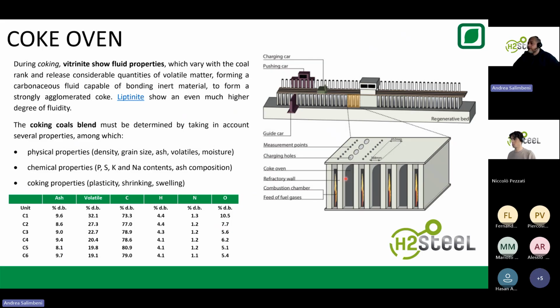These are the chambers where the coal is charged, and these are the chambers where heat is produced by burning the gas. In this case, at these conditions, the specific coking coal like vitrinite and liptinite becomes fluid and degrades, producing a highly porous, really strong carbon-rich material, which is named coke, which presents much more structural properties, compression strength and resistance than fossil coal. So these are the composition of the coal used in a mixture to produce coke. As you can see, volatiles are higher compared to those of the coal used for injection.